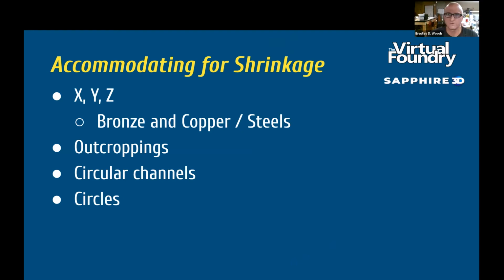Right. And what you're describing makes sense when you think of the densification process in terms of surface tension. If you were to picture this process happening in zero gravity and you took it all the way to the point where you melted the metal, you would wind up with a perfect sphere. So there are greater forces in a cube: the very extreme outer edges of the cube have more force on them than the parts that are more of a spherical shape.